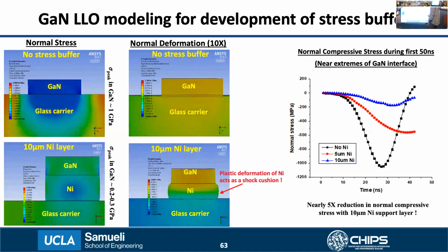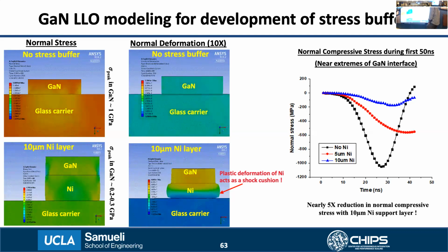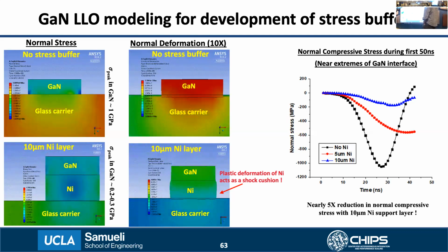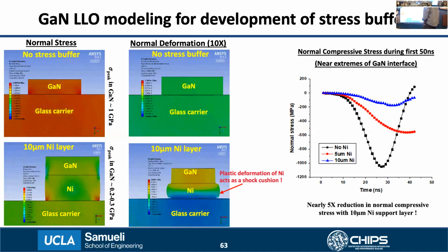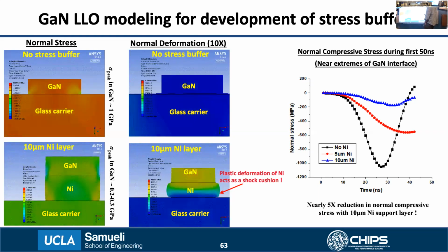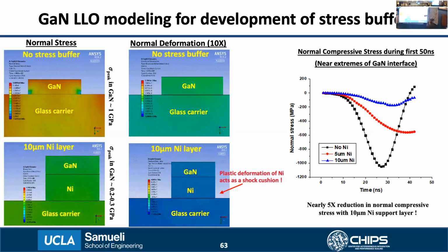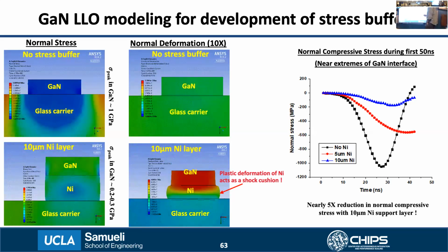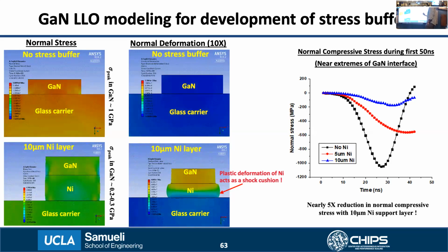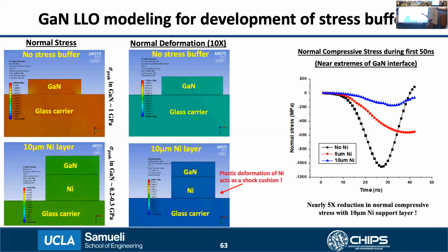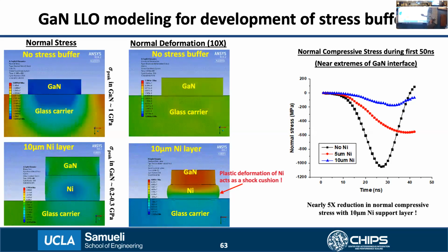On the right side, the graph plots the peak stress within the GaN thin film as a function of time for 3 different cases: when no nickel is used, when a 5 micron thick nickel layer is used, and when a 10 micron nickel layer is used. You can again see how the peak compressive stress falls rapidly as we increase the thickness of the nickel from 0 to 5 and then to 10 microns. So this modeling shows how the nickel layer would help in preventing stresses in the GaN film, thereby improving the yield of the LLO process.